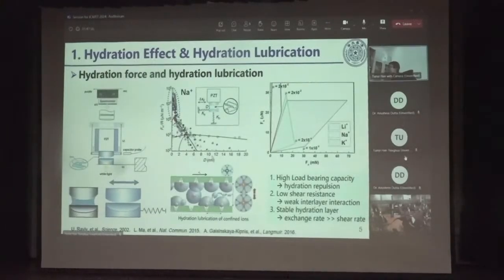Due to this strong hydration repulsion between two charged surfaces, in this literature, conducted by Professor Jacob Klein's group, they measured the repulsive force between two mica surfaces. Here are two mica surfaces, and the mica is glued on a silica lens. What did they find? They found a strong repulsive pressure as high as 10 megapascal if the distance between the two mica surfaces is very low, usually below 3 nanometer or below 1 nanometer.